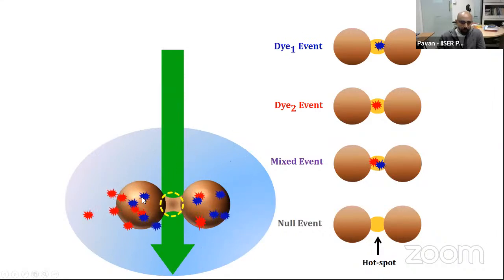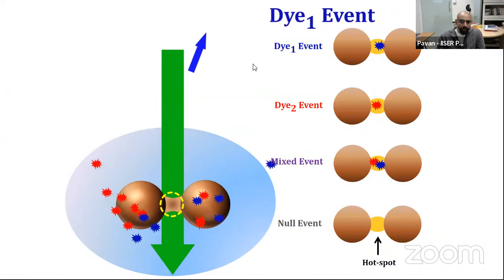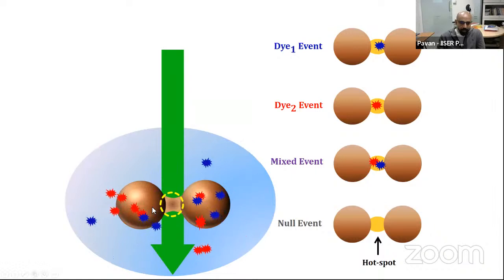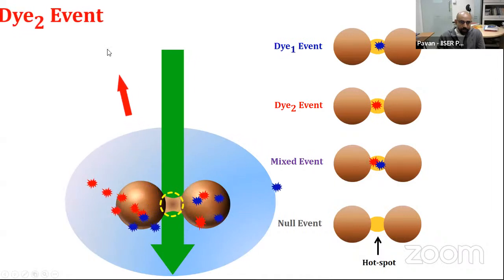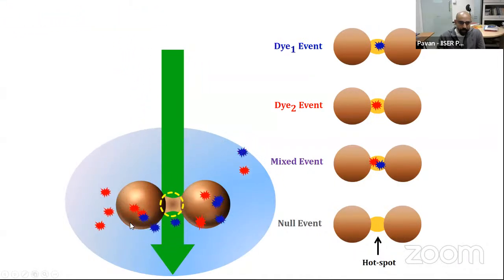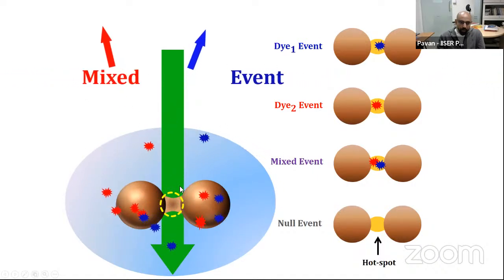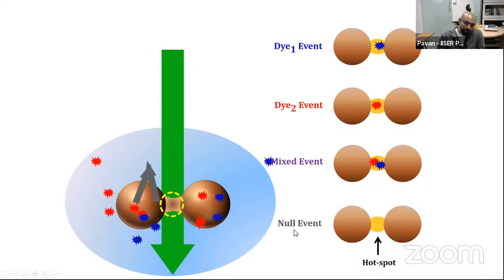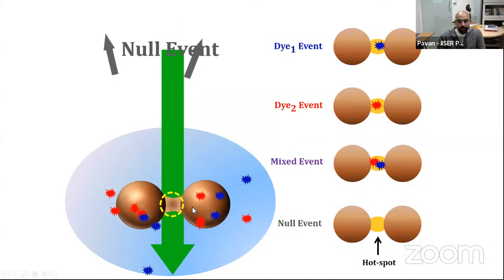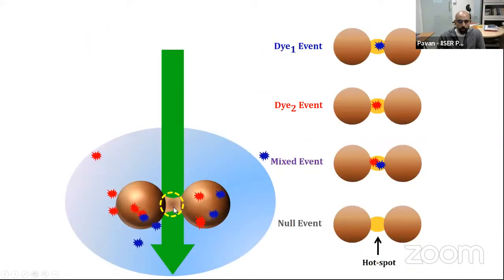So the technique is the following. You have now two different molecules, the blue and the red in this cartoon. When the blue molecule interacts with this hotspot in a trap, there can be a Dye1 event. And when the red molecule actually interacts with this particular hotspot, there can be a Dye2 event. Okay, and now there can be also an event where both the molecules actually participate, which is called a mixed event. So you actually have both molecule 1 and molecule 2 events, and of course there is another event which is essentially the null event. So what you do is, in this particular interaction for two different molecules, you now have 4 different events and you now track the probability of these events.